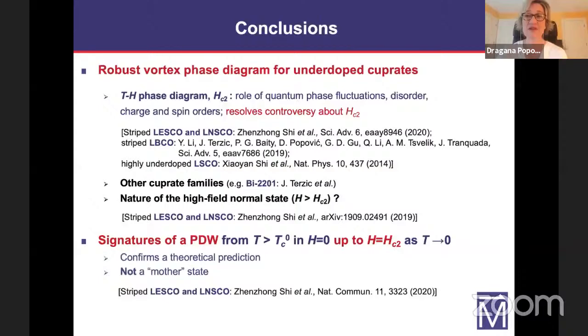So yeah, I don't have the answer for, say, copper moments, and also these studies have really not been done at very low temperatures. They're typically done down to 4 Kelvin or so. So there have been no probes in this regime. We have done some torque magnetometry measurements from which we are able to see that the Tc coincides with that you obtain from transport, but it's really hard to tell anything about what happens at higher fields because the signal is dominated by these rare earth ions.